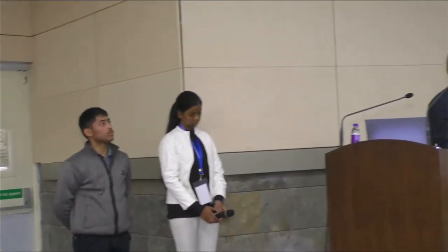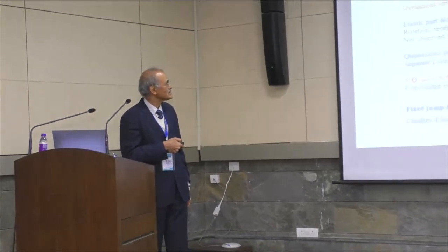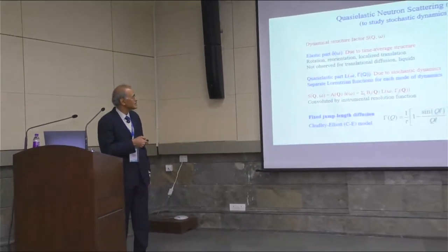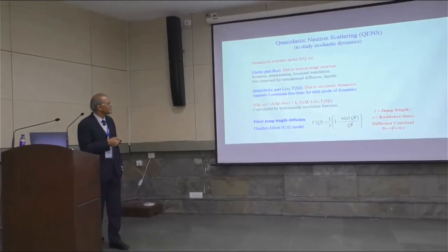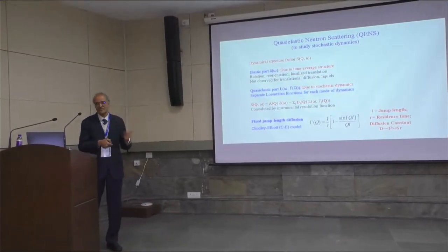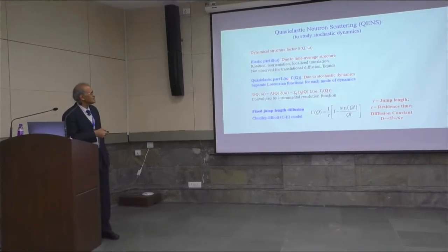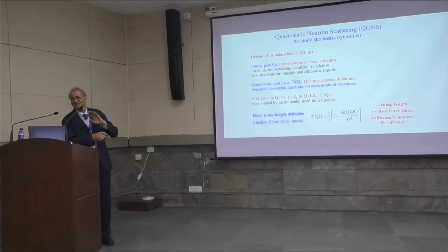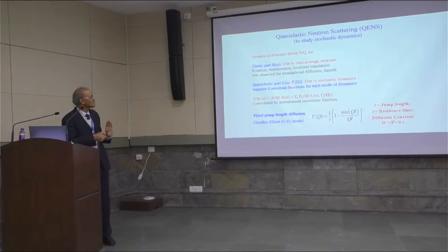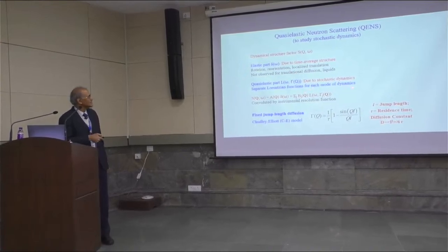Here again, there is an elastic part which is due to the time-average structure, and there is a quasi-elastic part. The broadening part we fit with a Lorentzian function, and the width of the Lorentzian can be related to the different kinds of modes of the dynamics. This is a fairly involved process, but I don't have to bore you with all that. It is just to give a flavor of the kind of things that are done. So you do the fitting and so on.